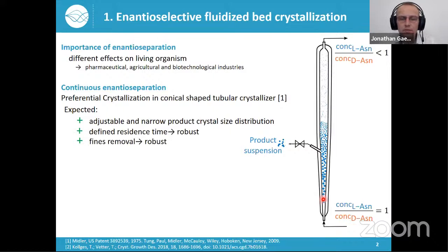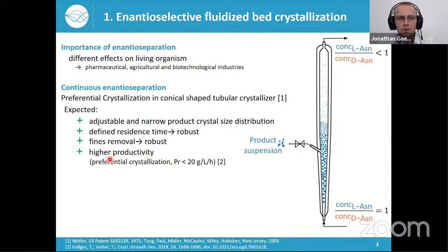Further, we have a very narrow and defined residence time distribution of our liquid phase, which is important since we have to avoid any nucleation of our counter enantiomer. But even if our counter enantiomer would start to nucleate, then we could expect that due to the size classifying effect, these tiny crystals will get discharged at the top of the crystallizer. So both these effects promise that this process is a bit more robust than, for example, stirred tank crystallizers. And this allows us to be a bit more aggressive, so we can set higher supersaturation to achieve higher productivities.